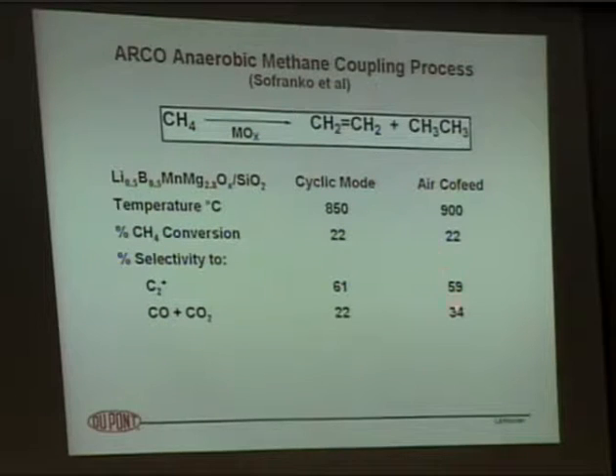And you can see two modes of operation. One is the cyclic mode, which is the anaerobic mode I've been talking about. They were able to get 22% conversion of the methane, and the selectivity to ethylene around 61%, and COx was 22%.